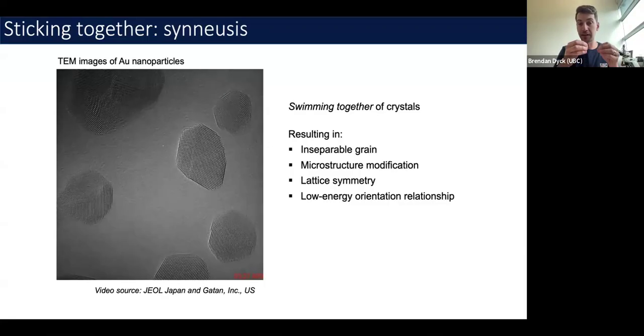So they maximize the contact of what becomes a very low energy portion of their grain boundary, in comparison to what the free energy would be of the grain boundary that's not touching the same or the other gold nanoparticle. So when we look at it on this scale, we can see we have these crystalline lattices, and there's this influence from that similarity in crystalline lattice, the orientation of these crystalline lattices as they meet. And the result is that after they come together, they generally form inseparable grains.